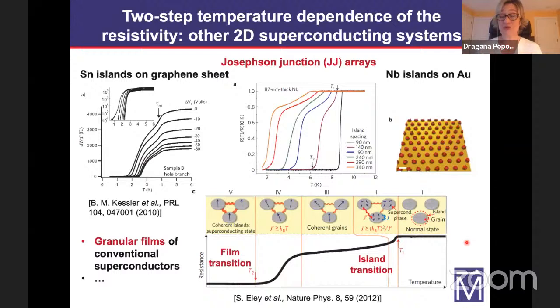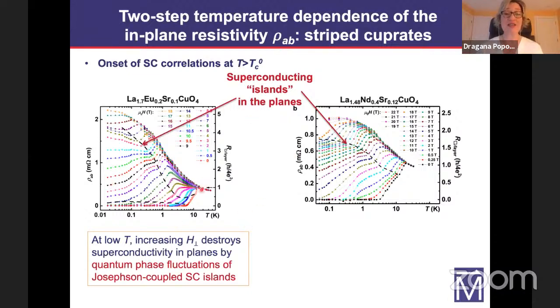So it is well understood from those studies that this initial drop of the resistivity actually corresponds to the onset of local phase coherence in the islands, and the TC, where resistance goes to 0, corresponds to the onset of the global phase coherence in the entire film. So in analogy to that, it seems plausible that this initial drop of the in-plane resistivity, where superconducting correlations start to set in the planes, we have some kind of superconducting islands or puddles. And in the same analogy, at low temperatures, as we increase the field, it seems that the destruction of superconductivity in the planes occurs by quantum phase fluctuations of these Josephson-coupled superconducting islands, and then at even higher fields, eventually the superconductivity in the planes is destroyed.